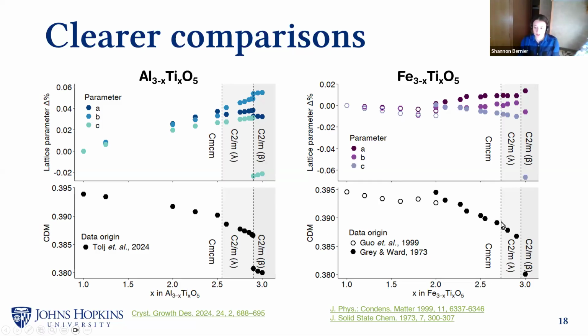There's a couple of interesting things here, which is again that we're still reproducing the discontinuities in the phase transitions, but also that there is a wider region of stability of this lambda phase in the aluminum compound when compared to the iron compound, which again can be a little bit obscured when you're just looking at the lattice parameter deviations here, because they're going up and down at the same time, as opposed to looking at a single function that goes down continuously. So I think in the case of the pseudobrookites, this across-materials comparison is something that was difficult to do before, and is something that we're hoping that the CDM can help with more in other parts of our field.